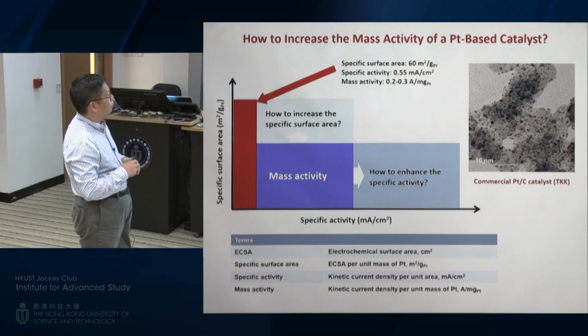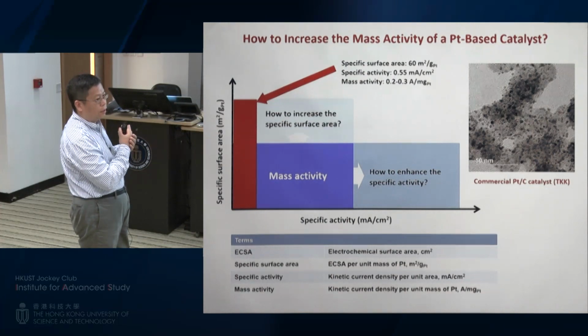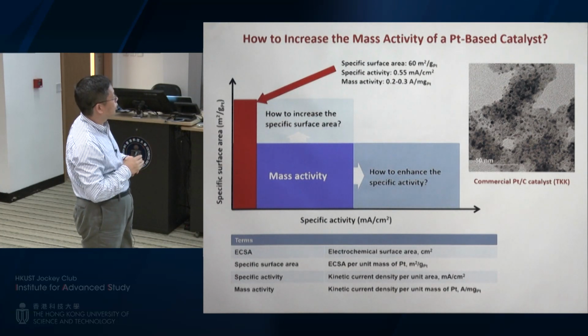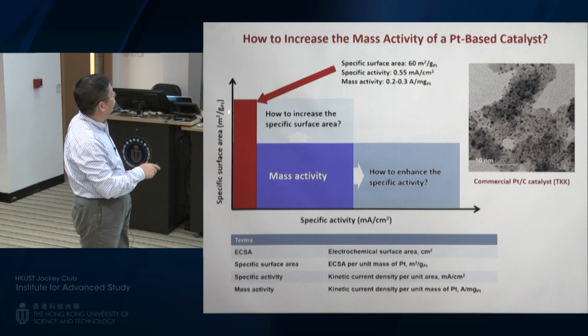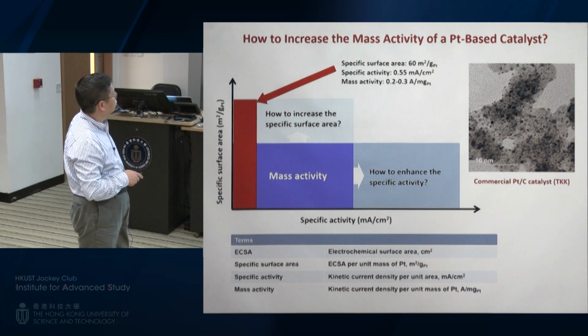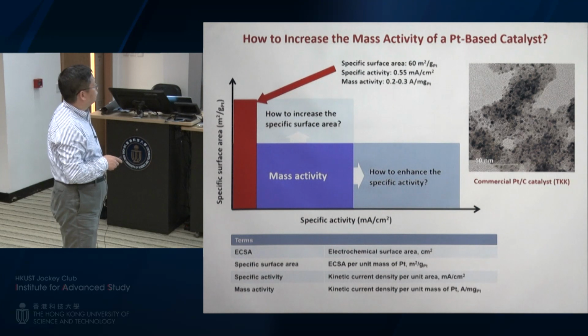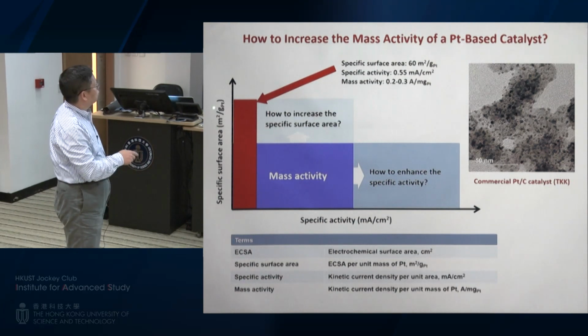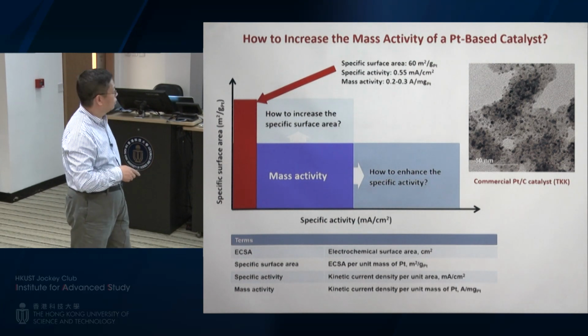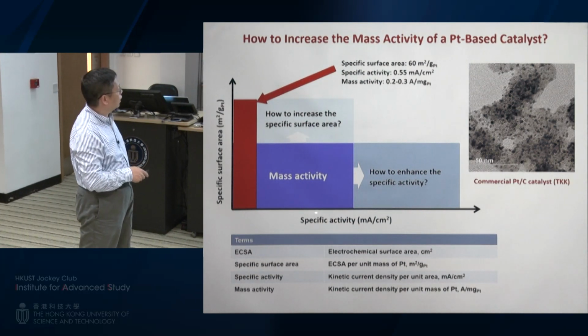You are going to have a lot of atoms located at the corners and edges that tend to be not good for oxygen reduction reactions. And so that's why overall the mass activity is not going to be great. Actually, it's only about in this region shown over here. So now let's see if there's any way to maximize both of them.